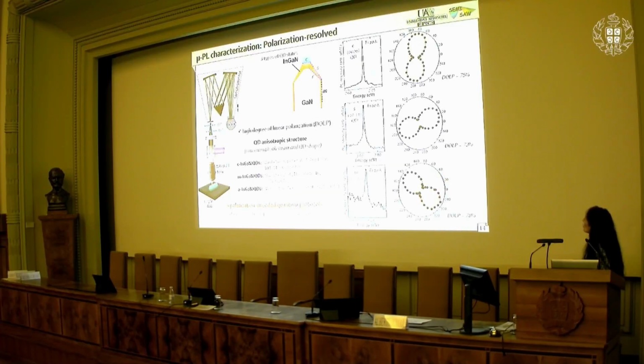We also performed polarization-resolved PL measurements for all types of quantum dot states, polar, semi-polar, and non-polar. And as you can see, they are all linearly polarized with an average polarization ratio above 70%. This high degree of linear polarization can be ascribed to a particular anisotropic structure of the quantum dot confinement potential concerning both its strain and its shape, as was previously reported for non-polar and polar indium gallium nitride quantum dots.